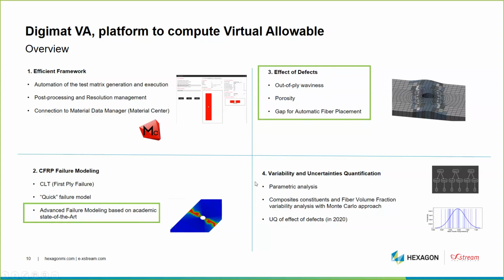And then, like I mentioned, when I listed the challenge, we have also the possibility in DigiMat VA to address the variability and the uncertainties quantification. So we propose capability to run parametric analysis. So that's not really variability, but it's just a discrete distribution or discrete value that can be defined here. And we can also address the variability at the composite constituent level and on the fiber volume fraction using a Monte Carlo approach.